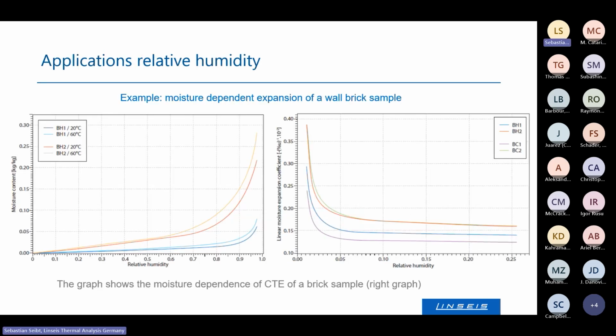Then I have some application examples. That was a study that a customer did. They were investigating brick samples at different temperatures. These were different wall brick materials, different quality and different batches. What they did is investigate the relative expansion using a dilatometer coupling. They looked at the relative expansion coefficient and the influence of humidity at different temperatures on the relative expansion.